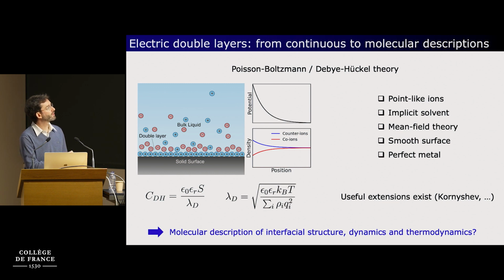And the canonical description that is already a century old is the Poisson-Boltzmann or the Debye-Hückel theory. It's based on point-like ions in an implicit solvent. You only consider electrostatic interactions and treat them at the mean field level. You consider a smooth surface, a perfect metal, and so on. In addition, you consider small potential differences. You can linearize Poisson-Boltzmann theory to get the Debye-Hückel theory, which predicts an exponential decay of the potential and the ionic density profiles as you move away from the surface. And the characteristic distance for this decay is called the Debye screening length, which is given here, which depends on the permittivity of the solvent and on the ionic concentration and the valencies.